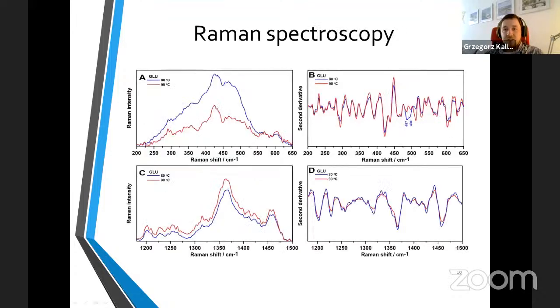And coming to results, in Raman, mean normalized spectra were quite similar. Here, presented in panel A, is the most distinct change, which is a change of intensity in the range of 200 to 650. To investigate it better, we performed a second derivative, shown in panel B, revealing two new bands attributed to a skeletal distortion and to ring vibration of carbohydrates in our sample gelled at 80 degrees. In other ranges, no notable changes of spectra were present.